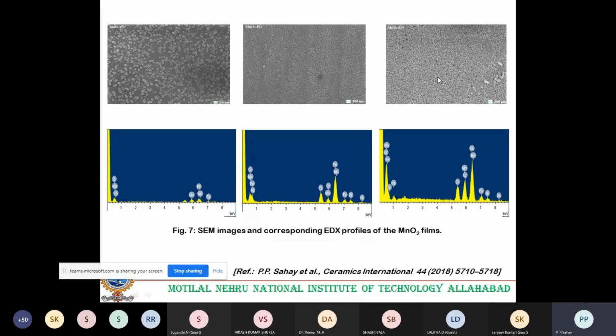So what I want to say is that the surface morphology of the MnO2 film is influenced greatly by varying the deposition modes, because all the 3 figures are not the same. Here the previous one behaves as a porous material which allows the electrolyte ions to easily diffuse through the electrode bulk, leading to an enhancement in the number of faradaic redox reactions. So this is the more favorable structure.